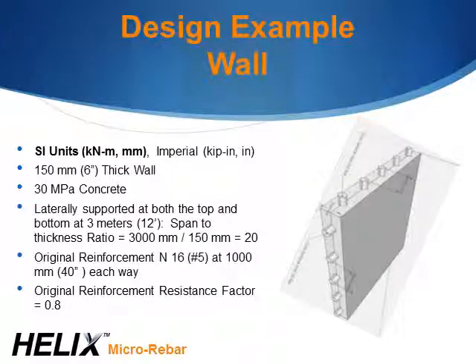So here's a simplistic example. I'm going to do this example in SI units, although the evaluation report, the design document, also has full examples in both SI and imperial units. So the same method applies whatever unit system you're using. We're going to consider a 150 millimeter thick wall that is made with 30 MPa concrete. It is laterally supported at both the top and bottom at 3 meter spacing. So one of the things that we want to calculate is the distance between the lateral supports. In this case, it's 3,000 millimeters divided by 150 millimeters, which is 20. So that span to thickness ratio is 20.